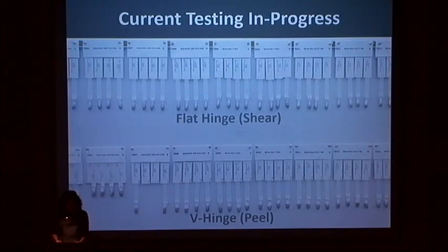Shear and peel strengths are respectively involved in flat, V hinges. Each card tacked to the wall supports 4 RC paper samples with weighted hinges. The 4 duplicates permit us to average results and measure standard deviation. We calculated weight based on the weight per area each hinge would support for most photographic prints. We selected a 20-gram weight, which is slightly more than heavyweight paper.